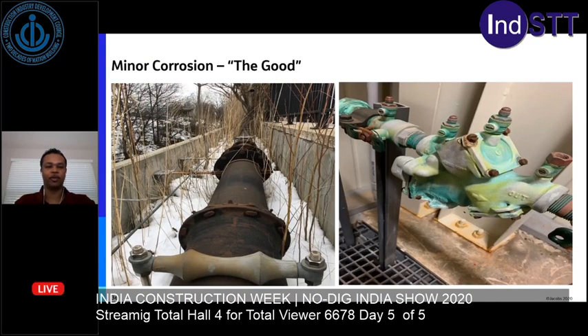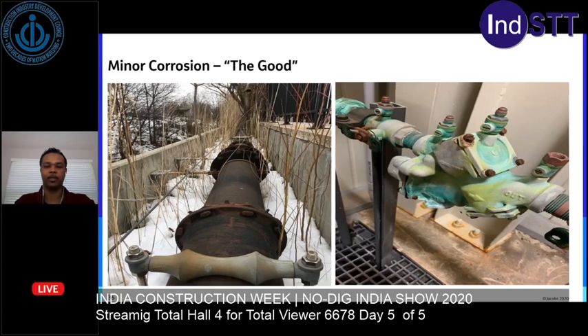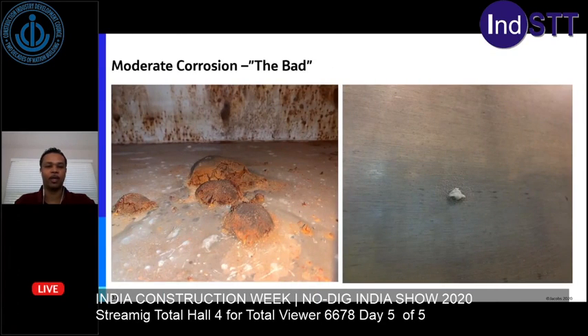Let's start with a couple photos that show minor corrosion. This is considered the good corrosion, if you will. On the left, you have some atmospheric corrosion that's taking place. This is typically general corrosion or uniform corrosion. And the photo on the right shows some galvanic corrosion. This is where two dissimilar metals were used and corrosion is taking place. So for now, this is considered the good. It will get increasingly worse as time goes on.